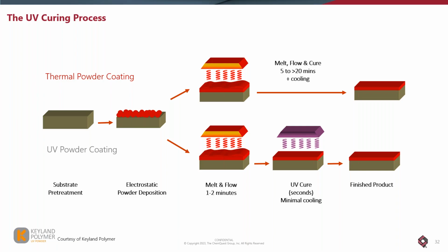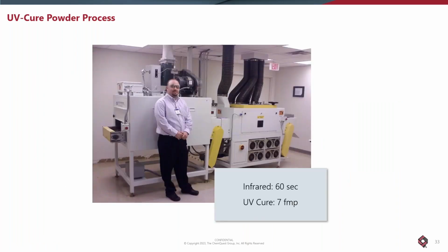So basically what you're doing is you're going through the same kind of application process. If it's an unusual substrate, you may have to look at that conductivity question, but you're applying some energy, typically infrared, maybe a combination of infrared and convection, to get your melt flow, your film formation that can happen quite rapidly. And then you expose that warm film to the right delivery dosage of UV energy, and you've got your coated product at a relatively low temperature cure.